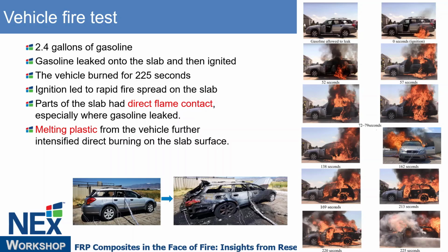Under the high temperature, the gasoline in the tank evaporated, and then due to the high pressure in the gasoline tank, there was a jet flame, which is considered a safety issue, so the firefighters stopped the fire earlier than we had designed. But in total the fire burned for 225 seconds, and in the test we can observe direct burning flame contact with the slab, so the overlay was exposed to the flame, due to the leaking gasoline over the surface. Also during the test, because the vehicle has a lot of plastic materials, those materials melt and fall down on the slab surface, which also have direct flame contact with the slab.